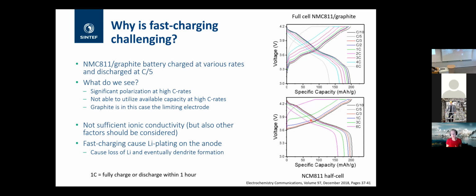Now, also very quickly before I go to the anodes, so why is fast charging challenging? That's something that often comes up in many discussions, and obviously also a great challenge for EVs or other applications. Now, in this case, this is an example where you have NMC 811, meaning that you have 80% nickel, 10% manganese, 10% cobalt, and you have a graphite anode. These are charged at various rates and then discharged at what's termed C/5, meaning that it's discharged within 5 hours. So 1C means it's fully charged or discharged within 1 hour.